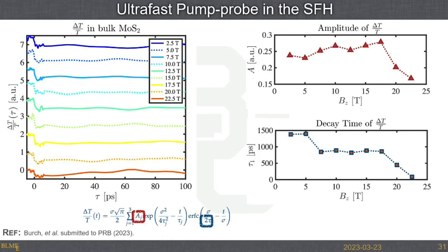And what we've been able to do is, if I've got these two monolayer sheets, I'm using the magnetic field and I'm actually torquing the various sheets. I'm actually using the magnetic field to twist these layers amongst each other. And it turns out there's a very efficient process that kicks in at 17 Tesla where I can control the electronic properties of these. So you're not going to have a 17 Tesla device, but this suggests going back and making these materials with some of these twist angles on there, and starting to use the twist angle from layer to layer to control the electronic properties of materials, which is a new phenomenon in materials.